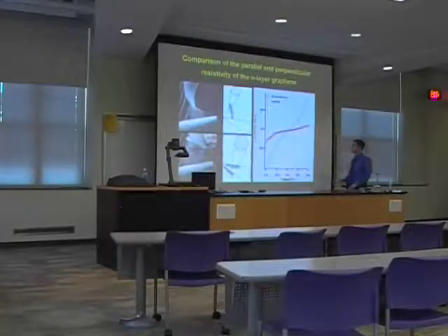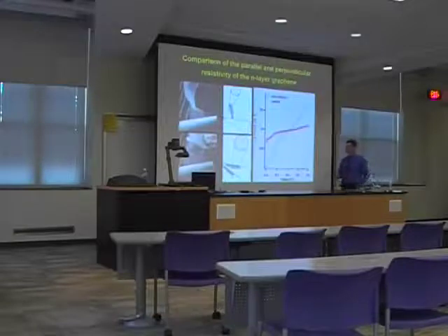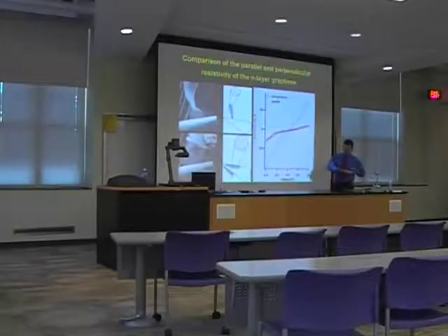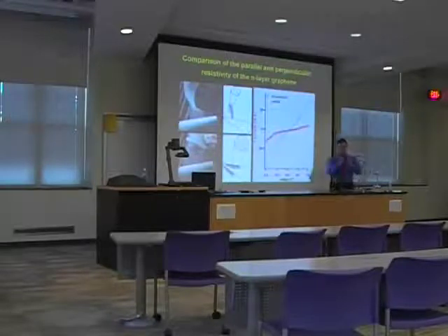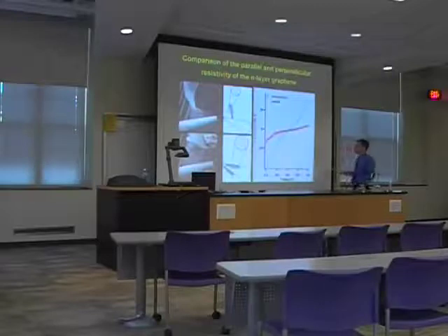Well, this is also a very interesting experiment. This is an example of anisotropic properties of graphene. Let's say if we measure conductivity along the layer, this is what I call parallel, you will get pretty high conductivity. But if you measure across the layers, across the two layers, you will see a significant drop of conductivity.